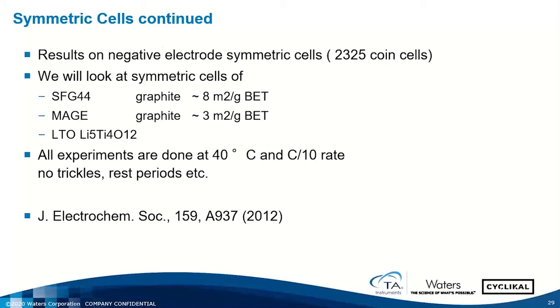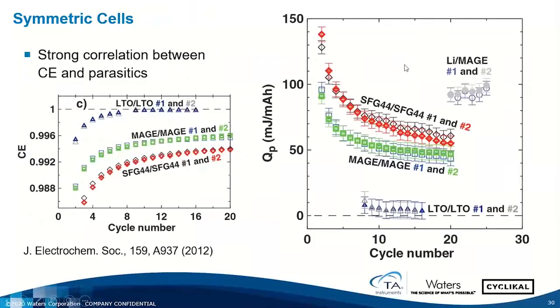All experiments are done at 40 C and at a C/10 rate. And this story is in this reference. All right, so on the right-hand side here, you see a plot of the thermal energy, millijoules per milliamp hour, plotted against cycle number.